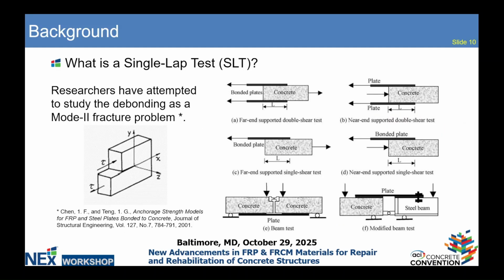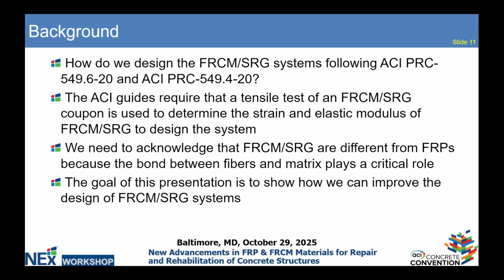As always happens with these composites, the main issue is the shear transfer. And in terms of testing the shear transfer, there are a lot of different tests. This is a well-known paper from the early 2000s where there was a description of all of them. And the single lap, which I'm going to be talking about today, is one of them. So it's basically a test where you have a block of concrete or masonry, the composite applied on one face, you restrain the block, and you are trying to pull off the composite. So this is the long background.